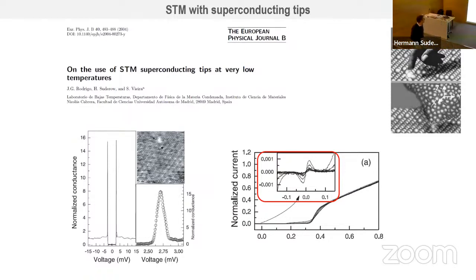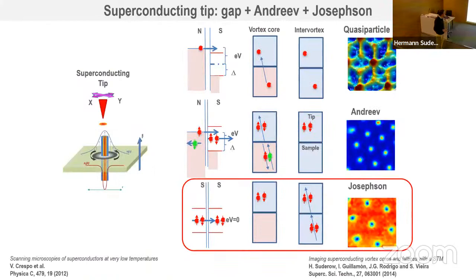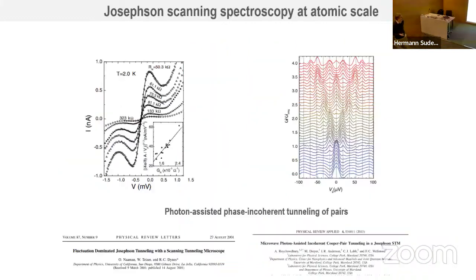And now to see Cooper pairs, you need a superconducting tip, and then you need to take a look at a tiny feature which is located here. This is the current, this is the voltage, and you look closely, there is a small peak. And the reason for the small peak is that through the barrier, there are Cooper pairs which tunnel. And this Cooper pair tunneling, you may trace as a function of the position. So here you have the vortex lattice when you apply a magnetic field. Inside the vortex, there is no Cooper pair tunneling. Outside, there is nice Cooper pair tunneling. So something which you can follow as a function of the position, and then you can get access to the Cooper pairs, which is something useful.